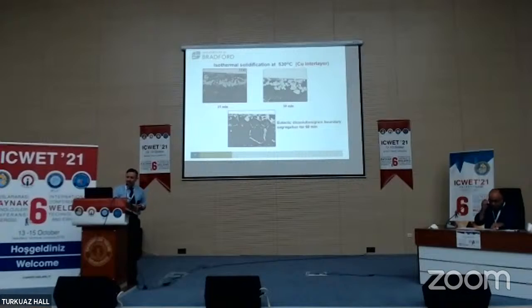And so what we find is that as we increase the bonding time, sometimes the isothermal solidification process tends to collect these intermetallics. So when the joint is forming, it first melts, and then when it solidifies, it goes in the reverse direction. So the intermetallics then move towards the joint interface. And this is what we tend to see in the last picture here. So some of this control and how we can do it is a big problem for us.